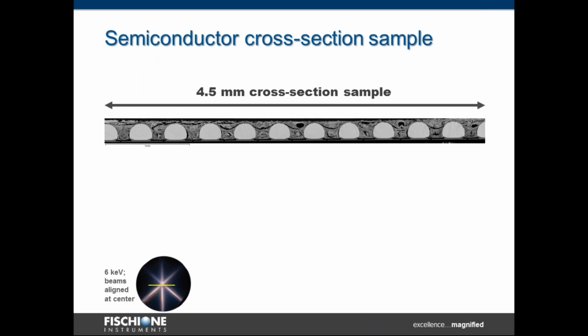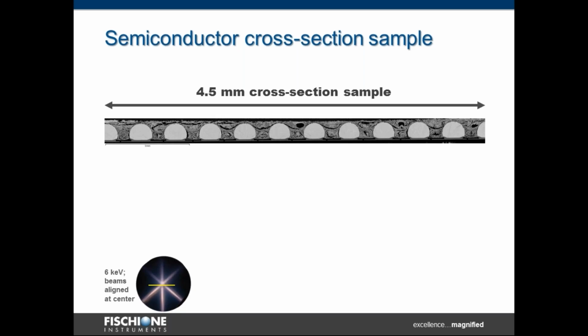So then I will move to the cross-section preparation. It's very demanding application, for instance, for failure analysis. And here we have the solder bump cross-section. This sample was not at all mechanically polished, just the mask was posed aligned at the center of the solder bumps. All material above the mask was removed by one cut using TrionMill.